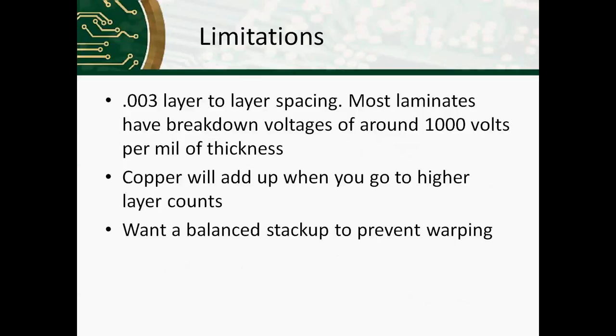There are some limitations that you need to be aware of when you're figuring out your stack-up. 0.003 layer-to-layer spacing is the standard minimum that we want to deal with. Most laminates have breakdown voltage of around 1,000 volts per mil thickness, and three mils we discovered is what will really ensure no chance of layer-to-layer shorts. There is two mil material available, but that is for some very specific reasons like embedded capacitance and should only be used for really specific reasons and consulting with your manufacturer.